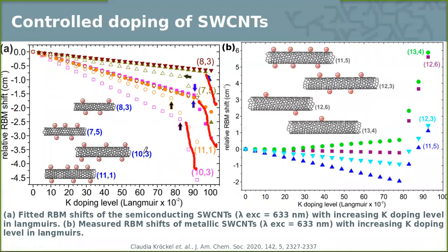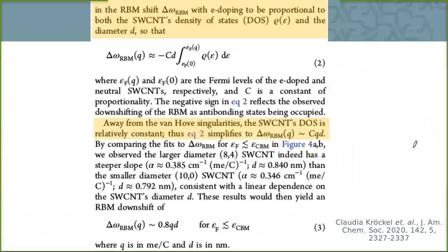So we proved that with this experimental result, because we got the kind of drop-down step, like we got it for the semiconducting sample. This is the semiconducting, and we got it also for the metallic sample, where we have this kind of behavior but going in the opposite direction of the shift. In this case, they behave opposite one to the other. So at this point, we started to make conclusions.